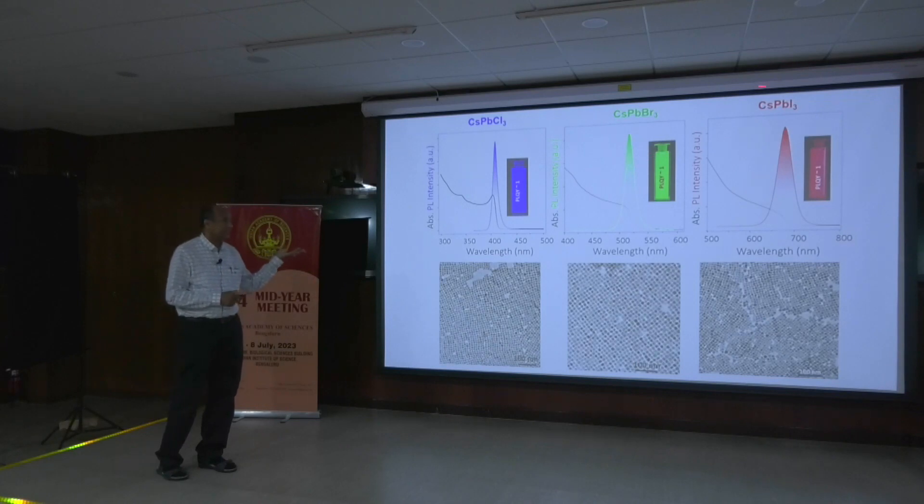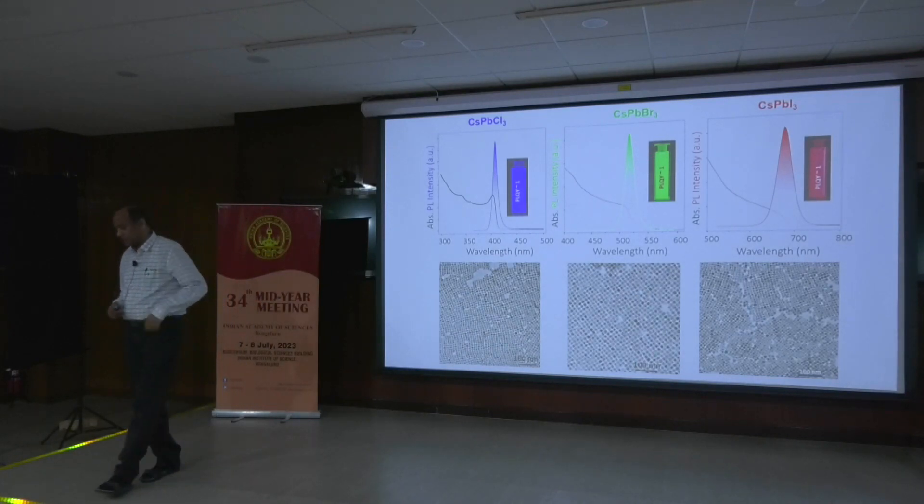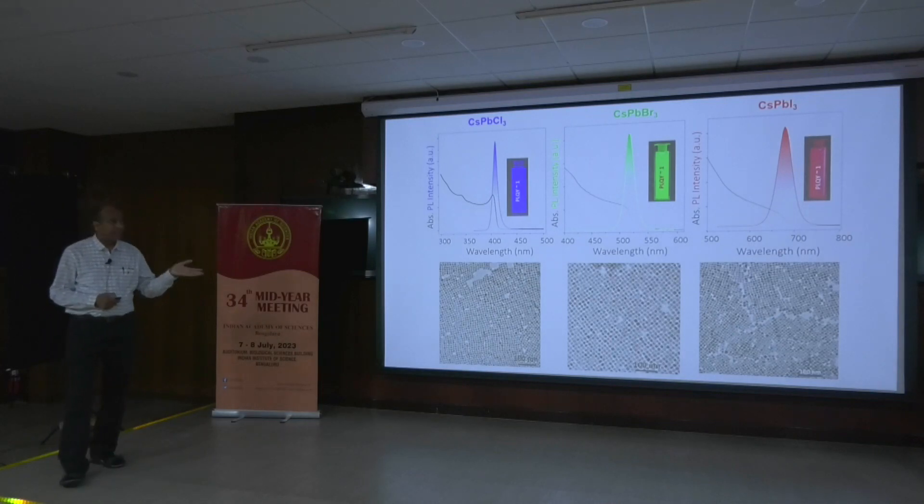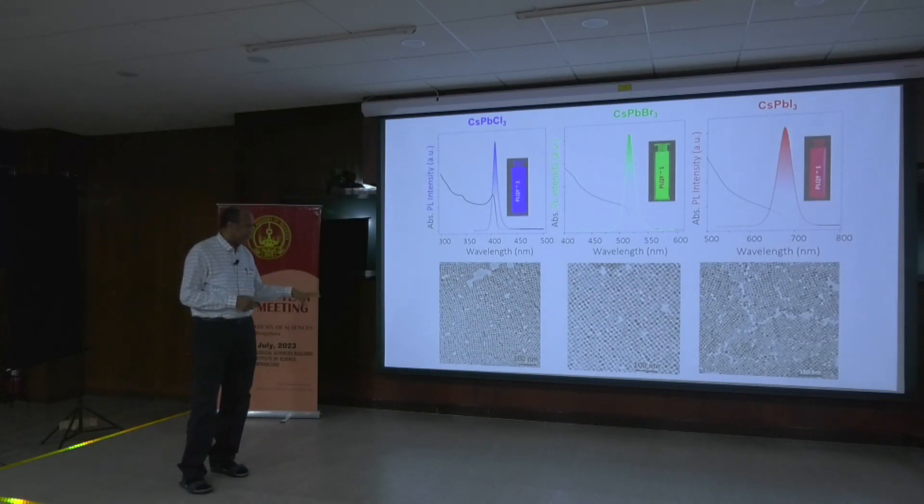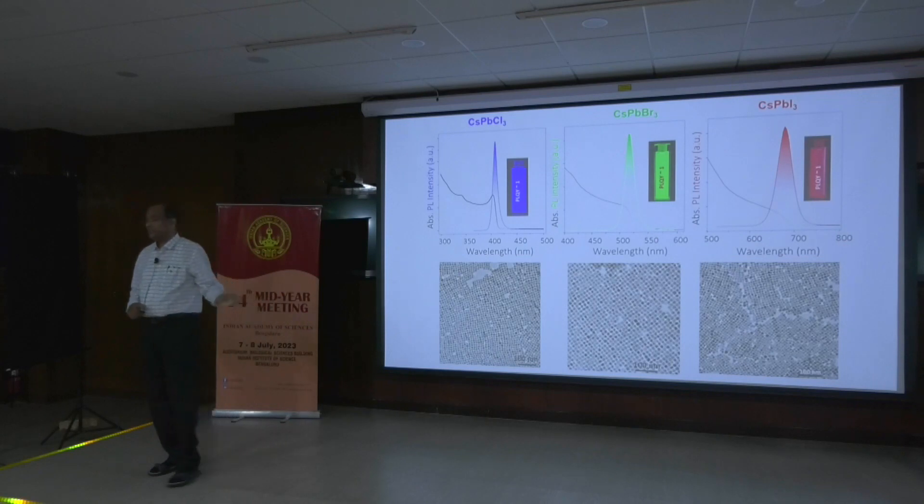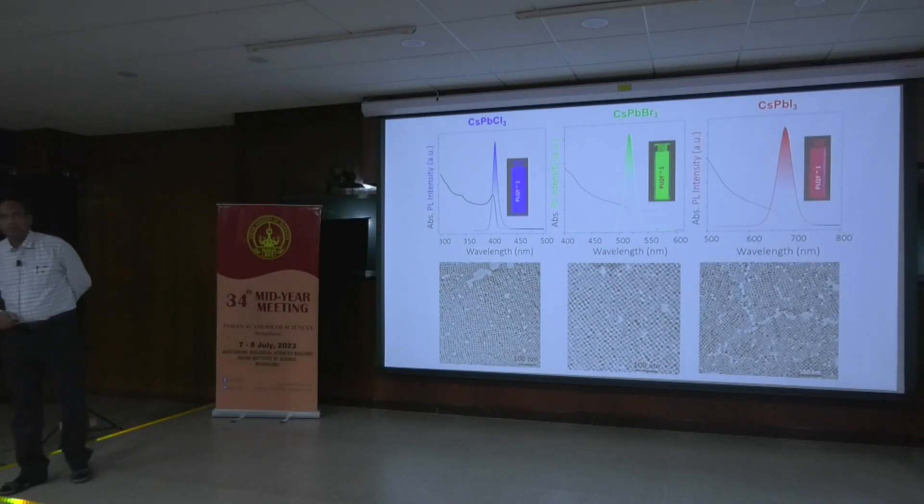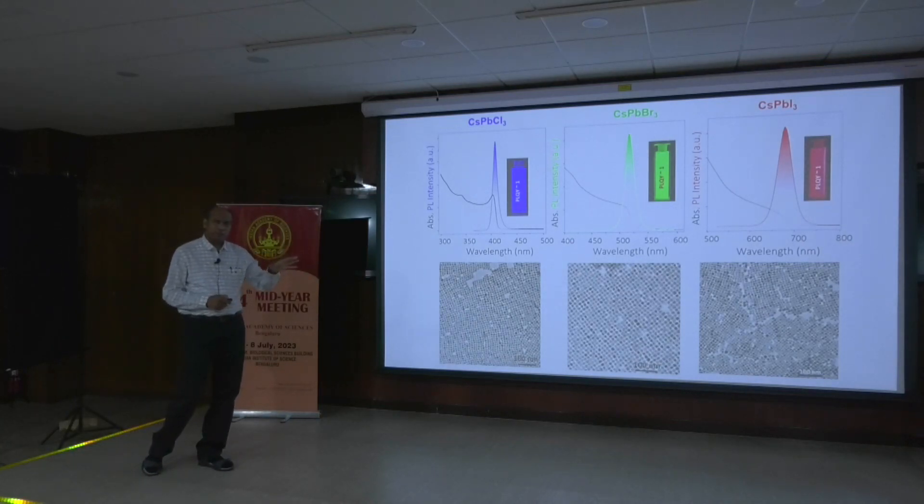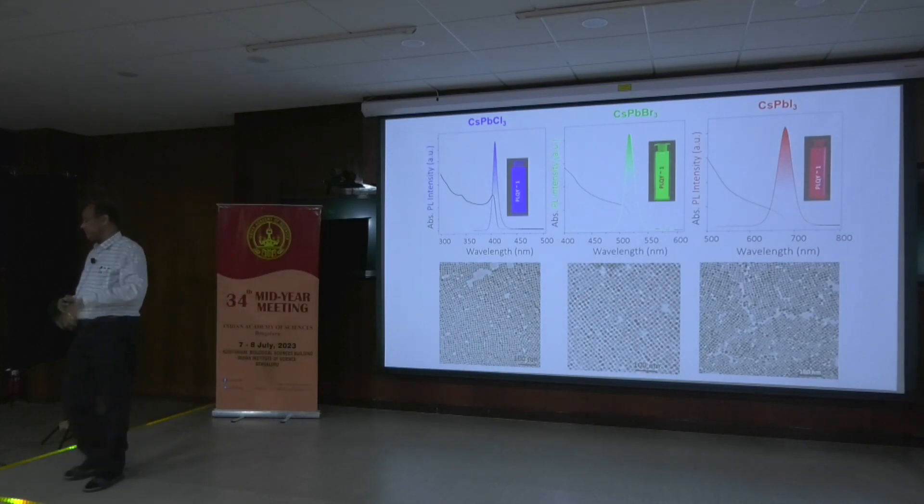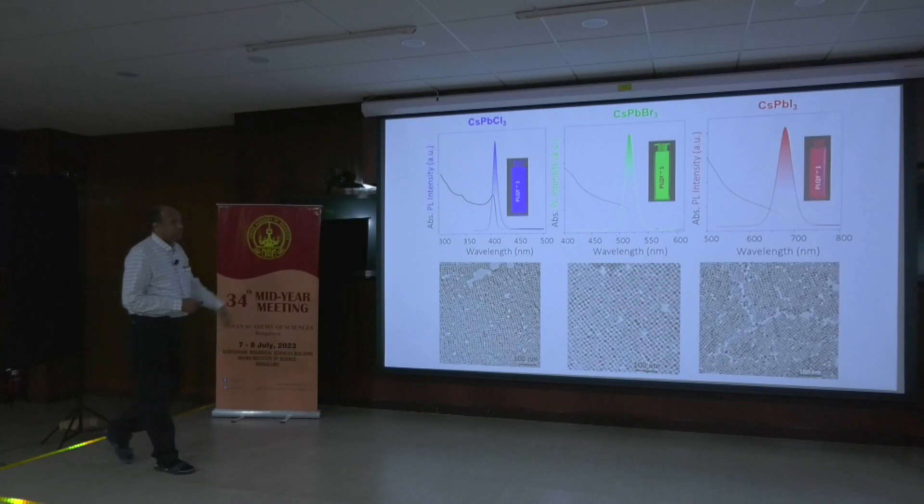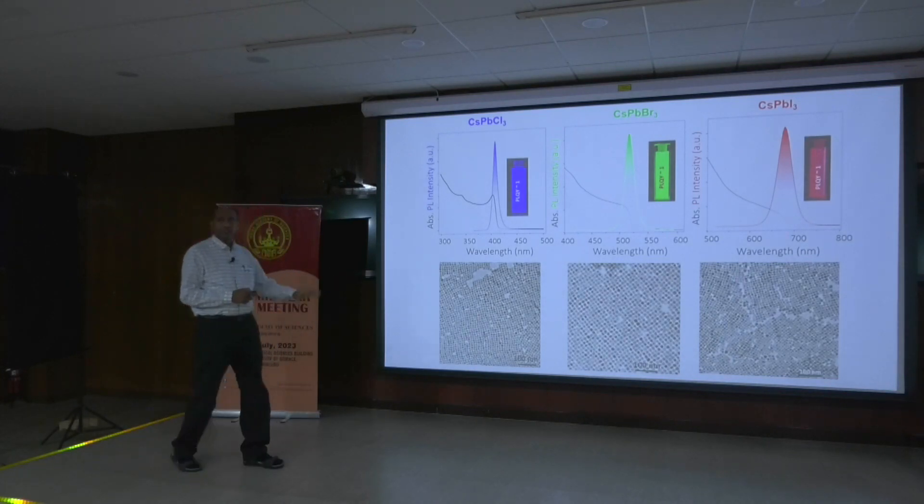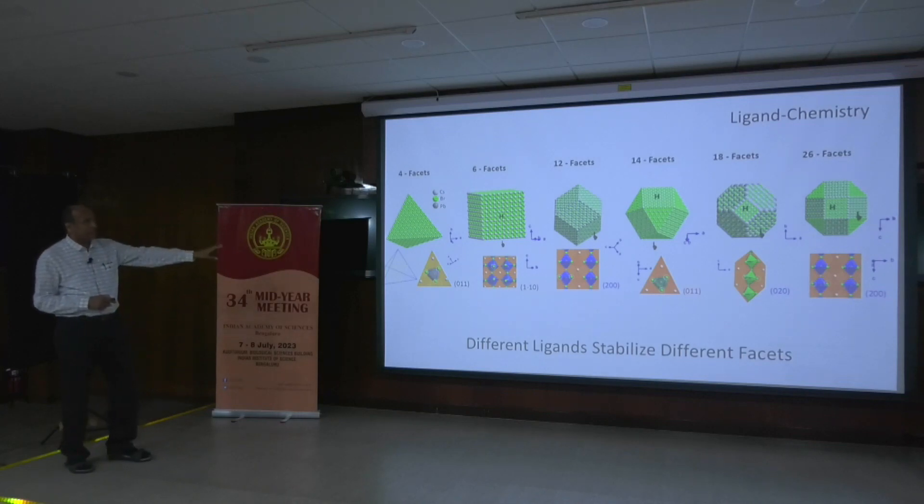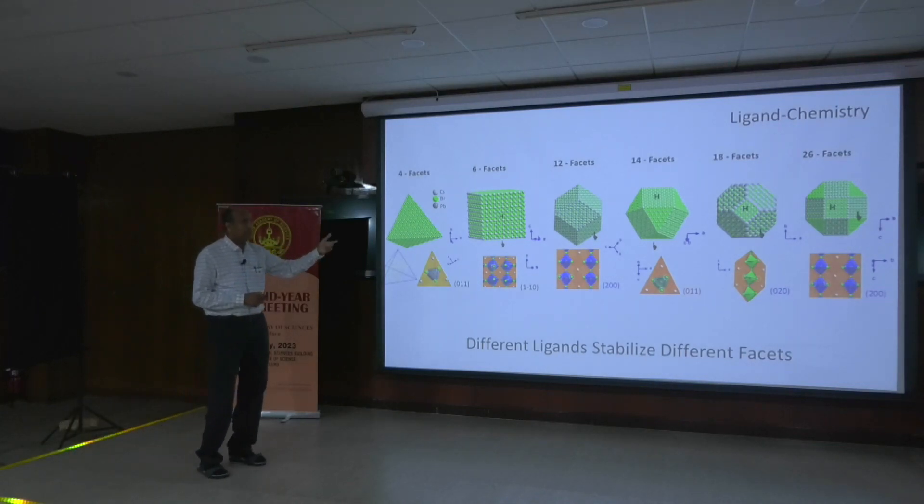Here I am talking about the three-color system needed for LEDs, backlight quantum dot LEDs. They are using indium phosphide, but these are upcoming if stability improves. These are much more robust and very intense. All are cubes. When we entered this field in 2015, about seven years ago, everything came out as cubes. Whatever you change, it comes out as cubes. If it is not a cube, no existence. That is the reason the question arises: how to crystal-engineer this to create new facets that might give new properties? I proposed in a perspective that everything can be possible on the surface if stabilized by organics.